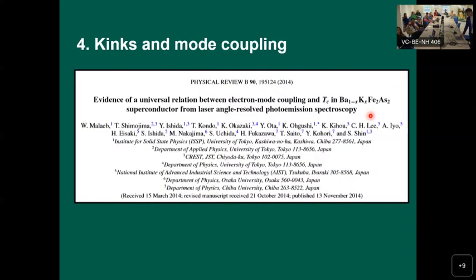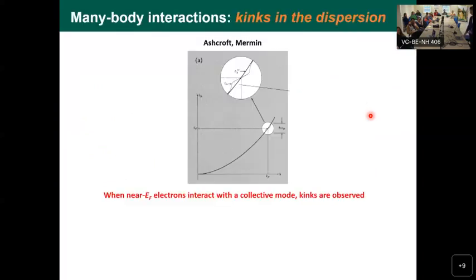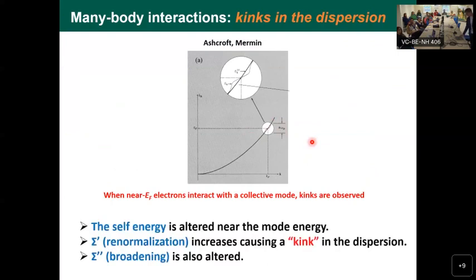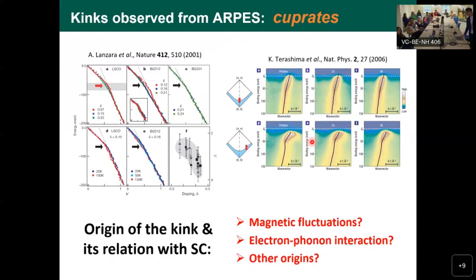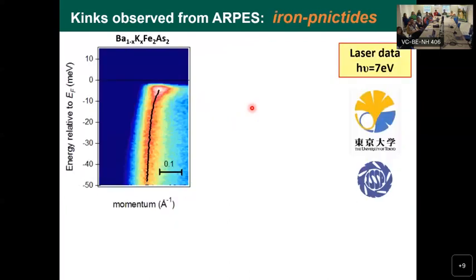One more thing we studied was the kink and the mode coupling, and here I usually like to show a figure from the famous solid-state physics textbook, Ashcroft and Mermin. Back in the 60s, they show the electron band, and if there is some additional interaction, it shows an anomaly. This is what we usually call the kink. It is due to some change in the self-energy and so on. This study was done for the copper oxides, the cuprates, back in 2001, 2006, and so on. We wanted to investigate the same effect for the newly discovered iron pnictides, and that was done with the laser.